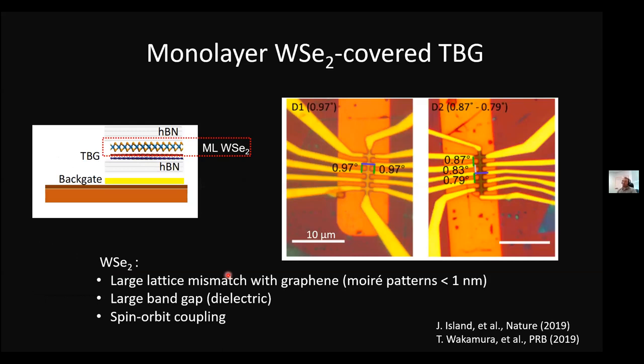So the way we make our devices is slightly different from other groups, and the main difference is that we use a monolayer tungsten selenide when picking up the first layer of graphene. So the end structure looks like this. You have your backgate, you have HBN on top and the bottom, and then on top, further away from the backgate, you have this tungsten selenide monolayer.